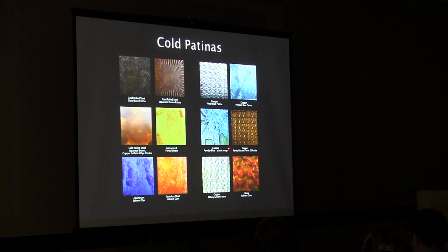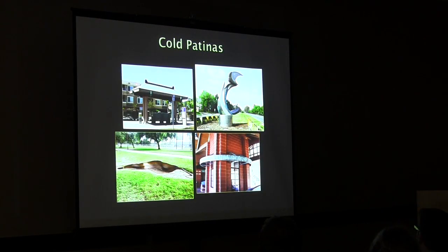So when you put them on something, this is a train station we did down in Carlsbad, California, and this was a laminate. We had copper over this laminate, and the architect wanted a patina, and we had 4 days to do a 10,000 square foot roof, and the interior here. And so we used our mint green. It's my favorite patina outdoors on copper. It's the most stable. It never changes. You don't have to worry about it, and I didn't even seal the roof. Luckily, it was summertime, so the roof was getting around 200 degrees, so it wasn't that difficult to do. It just went on easily. We put them on with sponges, those kind of mops, and it went great.